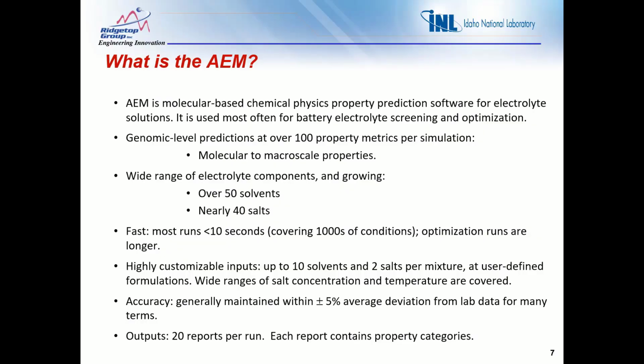It has over 50 solvents at this point and nearly 40 salts. These cover lithium-ion type battery systems, aqueous systems, as well as sodium-ion type electrolytes. The model is very fast due to the chemical physics framework. It runs most cases in less than 10 seconds, and these can cover thousands of different conditions of concentration and temperature. Optimization runs take longer.